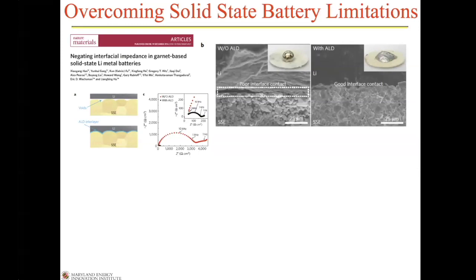The data to the left is the impedance spectroscopy. The data in red is the one without the ALD treatment. You can see it's well over 3000 ohm centimeters squared, very, very high impedance interface. By doing the ALD coating, it drops down to that little teeny black semicircle in the lower left corner, which we blow up to see what the impedance would be with the ALD.